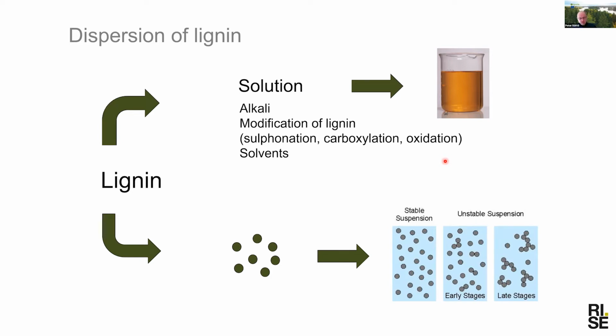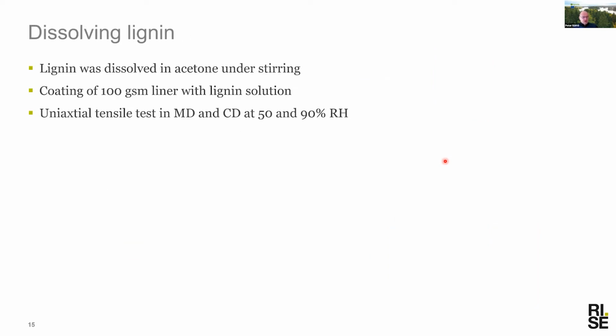The other way around is kind of to trick the system a little bit, that you put the lignin in particles somehow and you suspend them in water. And this is usually done by adding some sort of a stabilizer or surfactant that would place itself, have one hydrophilic end that will turn towards the water and one hydrophobic end that will turn towards the lignin. We have done other works with dissolving lignin in either acetone or isopropanol, and it works quite nicely.